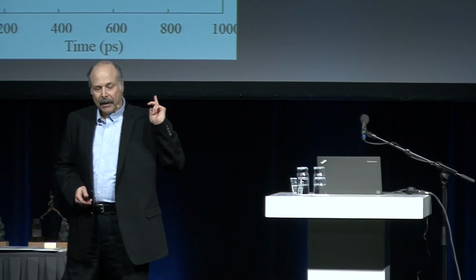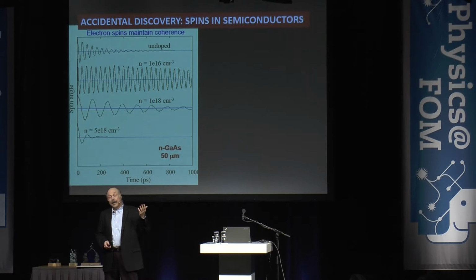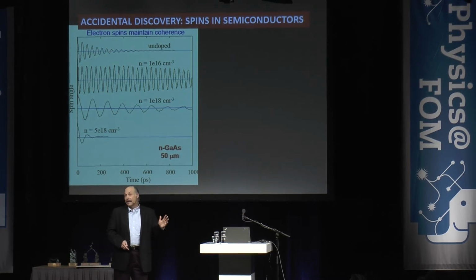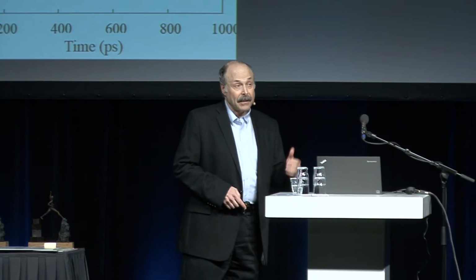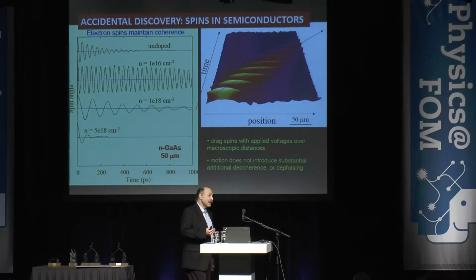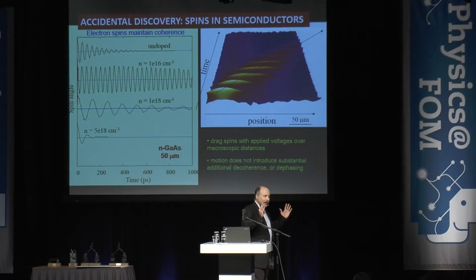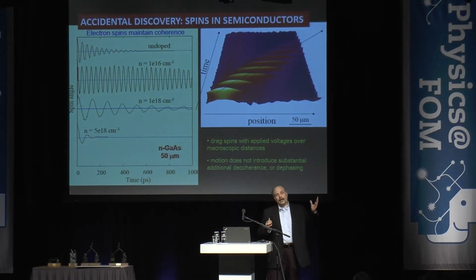And in fact, what this data shows at low temperatures is that based on the doping density of these wafers, the spin lifetime, or the coherence time, can be either very short, quite long, or very short based on the doping. A complete surprise that in just commercial industrial materials you could generate quantum mechanical states, in this case billions of them, and they would persist. And not only would they persist, but if you put on a small voltage across this wafer, you could drag these puddles of quantum states 100 microns or so through the material.